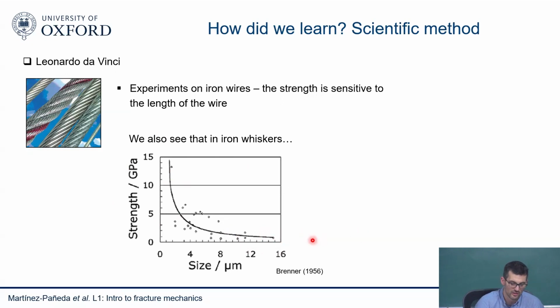But you can see that if you start going into small scales, look, we're looking into microns here, your strength appears to be very sensitive to the defect size. Up to the point that you can see the strength is roughly 10 times as large when we have very, very thin whiskers.